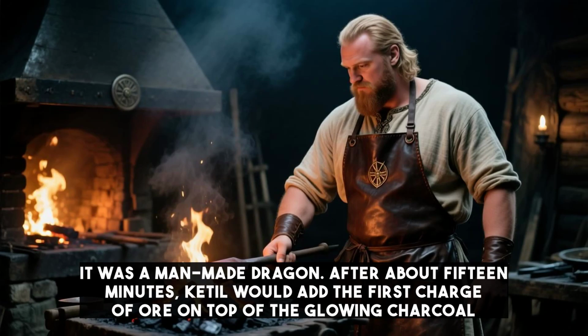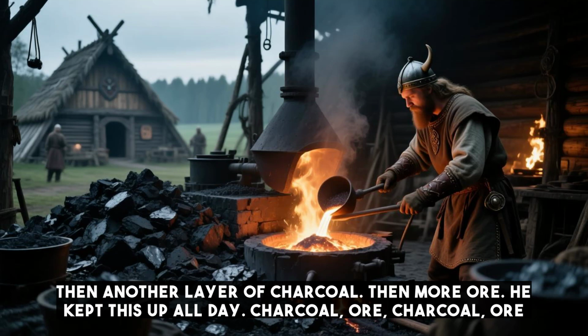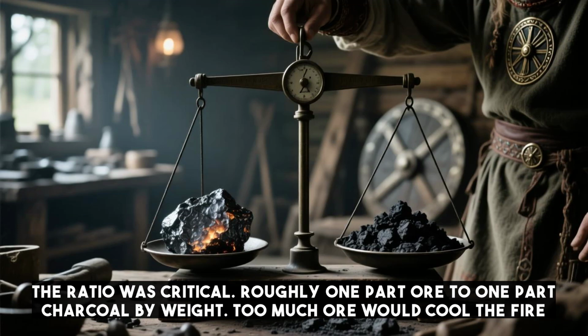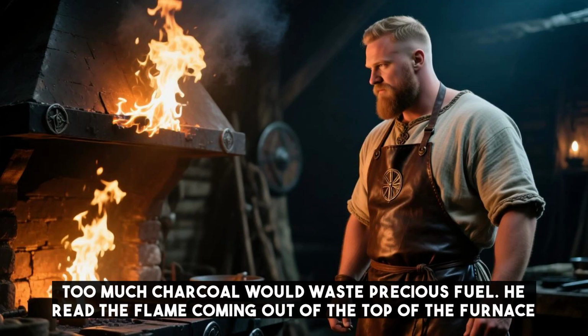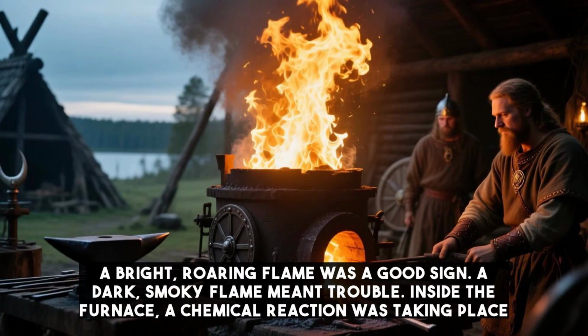After about 15 minutes, Ketil would add the first charge of ore on top of the glowing charcoal. Then another layer of charcoal, then more ore. He kept this up all day. Charcoal, ore, charcoal, ore. The ratio was critical, roughly 1 part ore to 1 part charcoal by weight. Too much ore would cool the fire. Too much charcoal would waste precious fuel. He read the flame coming out of the top of the furnace. A bright, roaring flame was a good sign. A dark, smoky flame meant trouble.